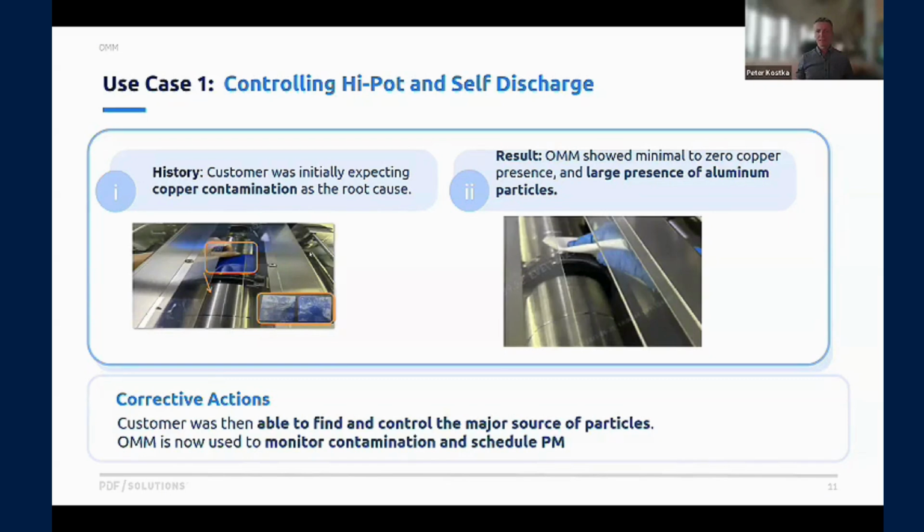That's effective, but in this specific case, their problems are so big, or maybe so far along, that they're looking for the big ones first to show, hey, is this what's driving our failures? And in that case, those particles need to be basically bigger than the thickness of the separator.